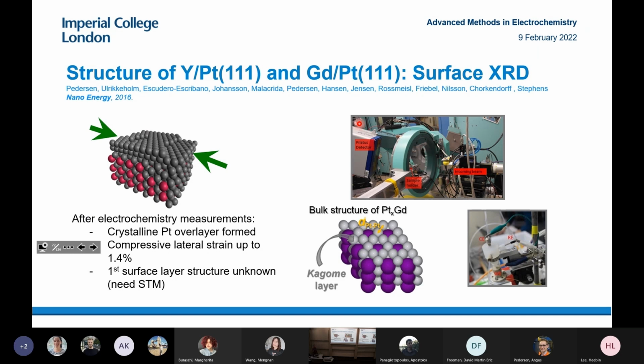And then we exposed it to electrolyte and measured what structure formed on top. What we found, to our surprise, is that even though we formed this complex structure that wasn't closely packed below, we formed a crystalline platinum overlayer on top that did resemble closely packed platinum. What we think is happening is that when you leach out the rare earth from this bulk structure, if you look here, it looks like you have something resembling a closely packed layer. So you can imagine a platinum layer on top of that would be like a closely packed layer. And in this bulk structure, the distance between platinum atoms is slightly smaller than in bulk platinum. So imagine a platinum overlayer on top of that would be under slight compressive strain.